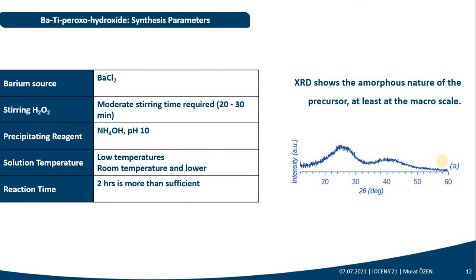When we study all of the results, Raman, infrared, XRD, and EPMA analysis results, we found that when we use barium chloride, when we stir the hydrogen peroxide solution for about 20 to 30 minutes, when we use the ammonium hydroxide solution as the precipitating reagent and adjust the pH of the solution to about 10, and use very low temperatures, room temperature and even lower, and the reaction time of about 2 hours, which is actually more than sufficient, we obtain a high quality precursor material for barium titanate.